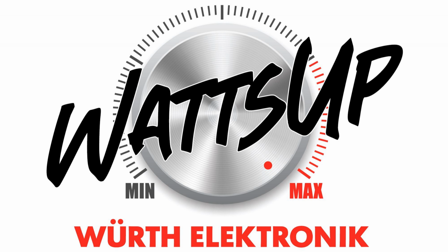Now, manganese zinc cores are inductive up to frequencies around 20 to 30 megahertz. Losses are usually rising above 10 megahertz, and the core material is no longer effective in the frequency range above 80 megahertz. And finally, nickel zinc cores are inductive up to frequencies around 60 megahertz. If we keep increasing this value, the core material is no longer effective above approximately 1 gigahertz and beyond.